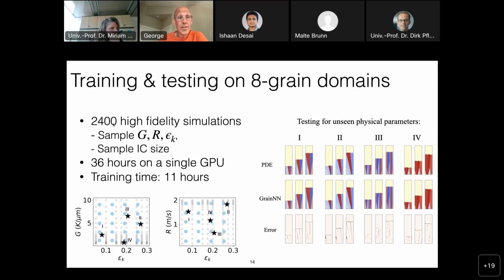Generating these 2,400 phase field simulations on the 8-grain took about 36 hours on a single GPU, and then training the network took about 11 hours. So if you have multiple GPUs, of course, it's embarrassingly parallel. You can make it as fast as you want to generate the data. And then training took, as I said, 11 hours on a 3 GPU system at Texas Advanced Computing Center.